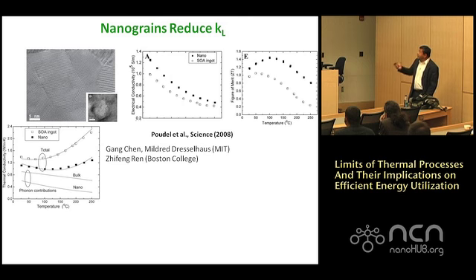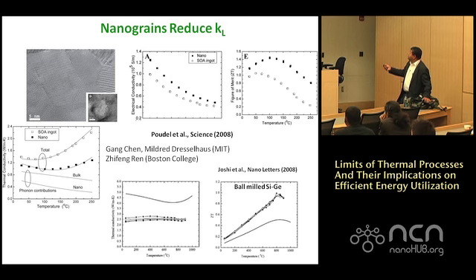So we started looking at that, and Gang Chen and Millie Dresselhaus also looked at that in the last couple of years. They said, instead of making this high MBE thing, why don't we just make nano stuff by ball milling, put them together, sinter this damn thing, and see what happens. What they found again was reduction of thermal conductivity without affecting the numerator, the power, the electronic side. And they did it for bismuth telluride, they did it for silicon germanium, and they showed that you can actually increase ZT greater than 1. And about 1.4 or so, just like we have done for indium gallium arsenide. This is silicon germanium, that is bismuth telluride, etc. So again, it was all phonon engineering.